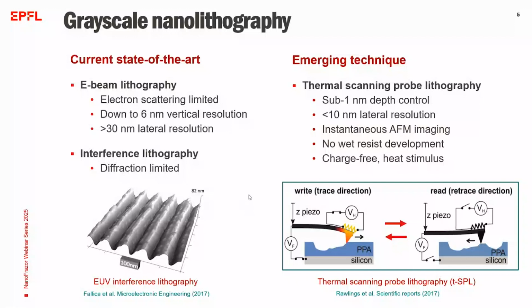TSPL offers lateral resolution below 10 nanometers, 1 nanometer precise depth control, and on the other hand, it eliminates the need for additional development steps by directly sublimating the thermally sensitive resist. Furthermore, being both electron-free and charge-free, this technique is ideal for patterning on sensitive devices like 2D material-based devices.